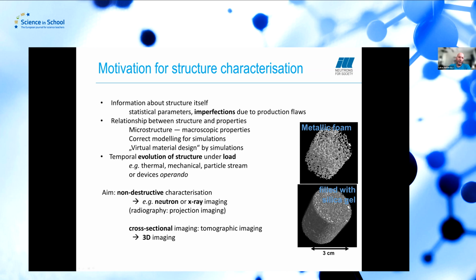So, and for that, neutron or X-ray imaging, as Alessandro has already shown, are very nice methods, because you get projection images in the radiography. So you see what happens inside the structure, and if you afterwards combine it with cross-sectional tomographic imaging, taking different viewing directions of the sample, as Sandro has already shown, then we can get to cross-sectional imaging without destruction of the sample, and to 3D imaging, so that you have any possible direction of cut through the sample that you can look at and even see the structures in 3D.